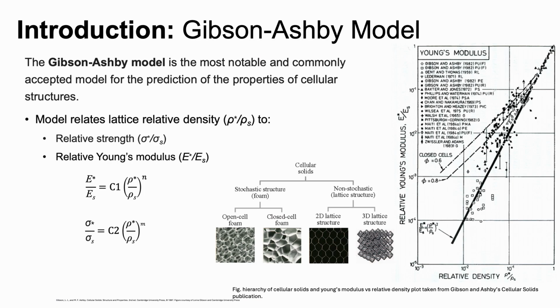We can actually predict the modulus and strength of lattice structures through the use of the Gibson-Ashby model, which is widely accepted and used amongst researchers for numerical modeling predictions of cellular solids. The Gibson-Ashby model relates the relative density of a cellular solid to its relative strength and relative modulus using this equation below. Previous work from Gibson and Ashby along with other researchers can actually be seen from this plot here to the right, where they used experimental data to fit their curve. And we can see that as relative density increases, the relative modulus increases as well.